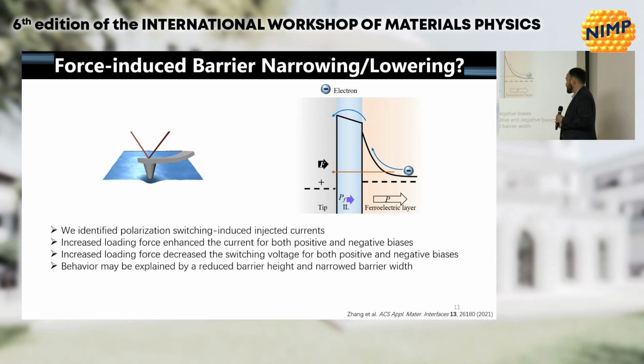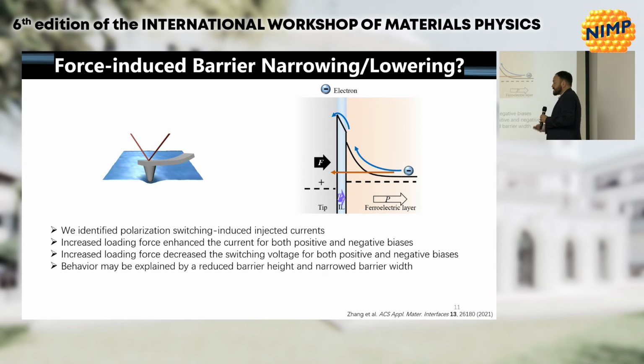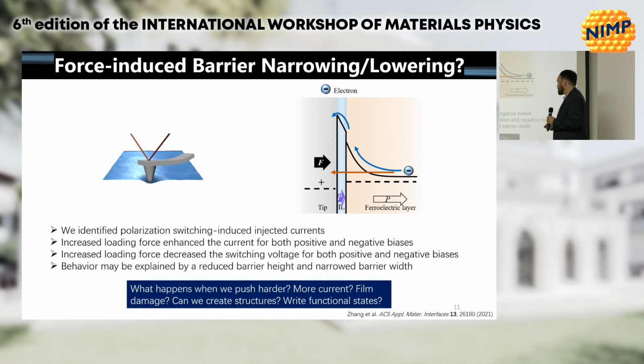So we believe that this could be explained by this reduced barrier height and narrowed barrier width, kind of as shown schematically here. Okay, then the interesting thing to think about is what happens if you apply even more force? Can you get more current? What's the limit? At what point do you deform the sample? We didn't fully go down that path, but I'll show you what we did do.